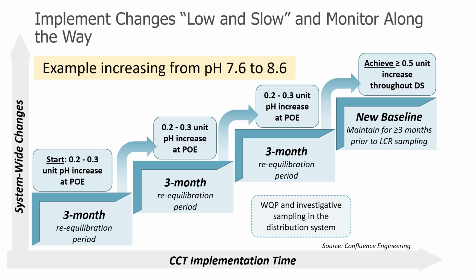Changes that are going to be implemented, low and slow is really often the way to go. Low and slow and monitoring along the way. So if you're going to, for example, need to increase from pH 7.6 to 8.6, you might need to do this in multiple steps, allowing about 3 months, we would suggest, of an equilibration period before each change, and doing water quality parameter investigative sampling all along the way until you've reached your target, and then maintaining that target for a minimum of 3 months, ideally 6 months, prior to doing lead and copper rule compliant sampling. We've observed that copper can react fairly quickly to distribution system changes for corrosion control treatment, but lead can really take months to form the protective scales that we're looking for.